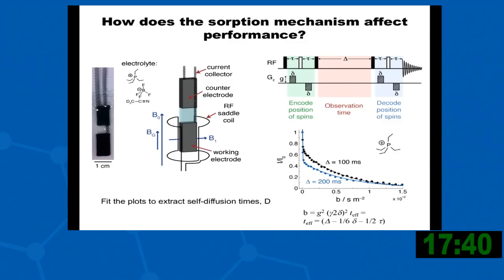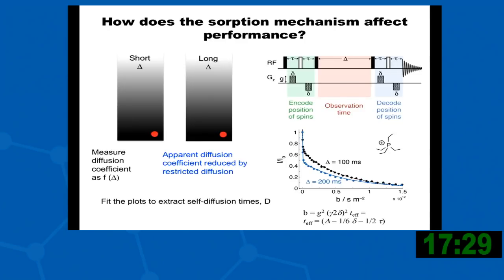So what are the implications of these mechanisms for charging? Well, to look at that, what we did was to measure how fast the ions move inside these pores, and we can do this with the so-called pulse field gradient measurement. And what you do is you put a gradient across a system and you measure the decay of the NMR signal as a function of time.